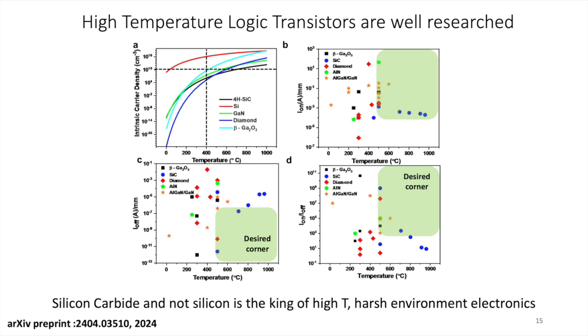Of course, the on-off ratio is not very good at 900 degrees Celsius, but that happens to everything when you raise the temperature. But even if you consider up to 800 degrees Celsius, they can get an on-off of about 300 or so, which means you can do quite reliable computing up to 800 degrees Celsius without any problems.